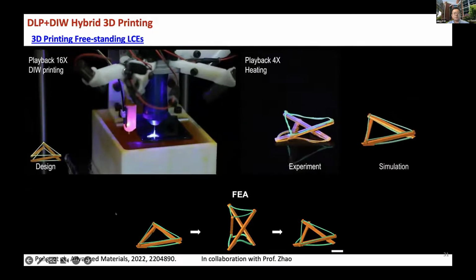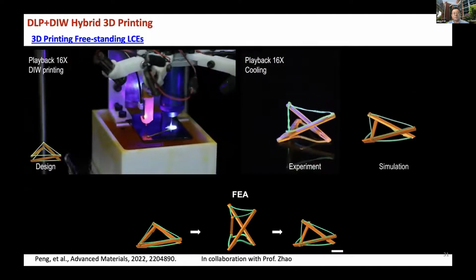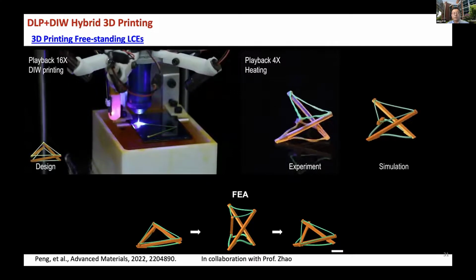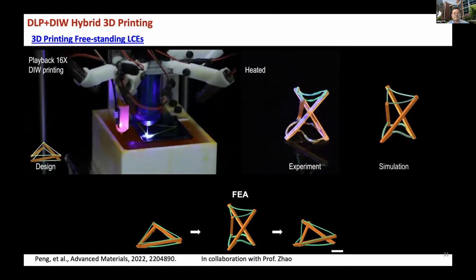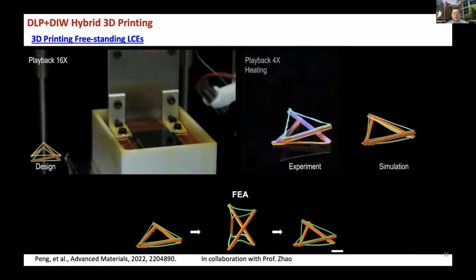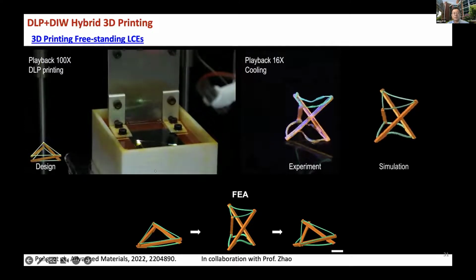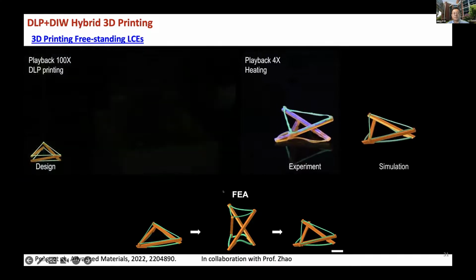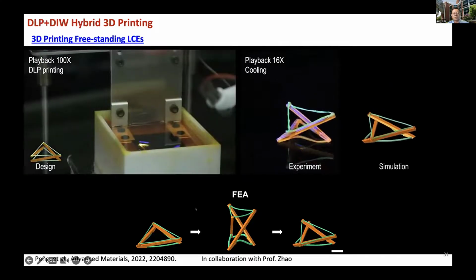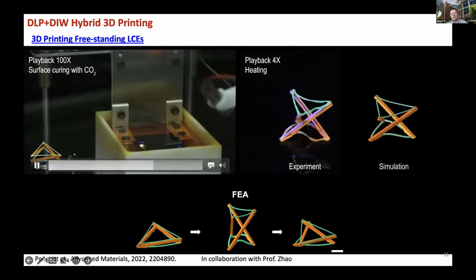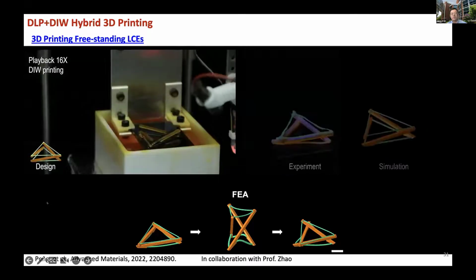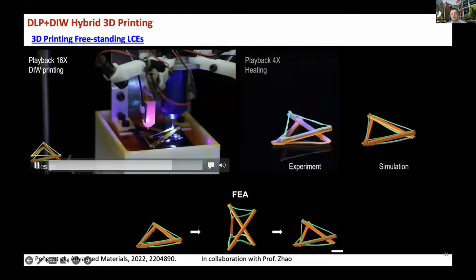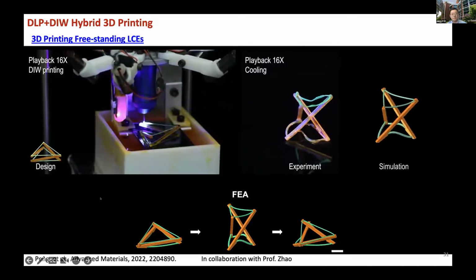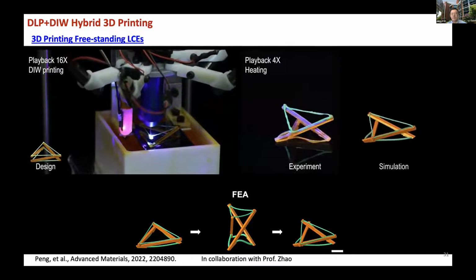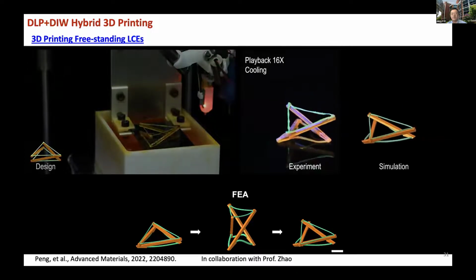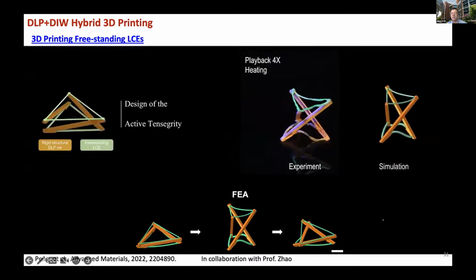And so here he actually printed the first bottom layer of the liquid crystal elastomers. And then he printed the rods. In this case, he made the rods very stiff, because you can see here, when you take it out, this rod is actually very slanted. And so you really need a very stiff material, otherwise this rod will not support its own weight. So now he printed everything on it. And then you can achieve this actuation, just take it out after print.